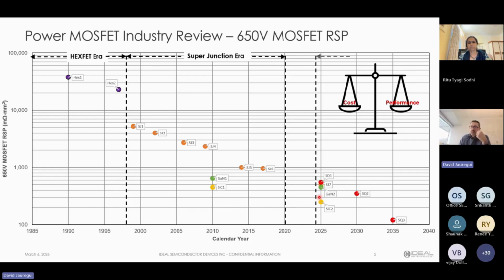But not only that, it was not going to be a one trick pony, meaning that it's just that and there was no path to improve. Based on our roadmap, we see a path to almost 100 milliohm millimeter squared, meaning that this technology that we developed, from a resistance per unit area, we believe will keep up the pace of the improvements seen by the wide bandgap technologies. For that one metric, we think that we're in a good position.